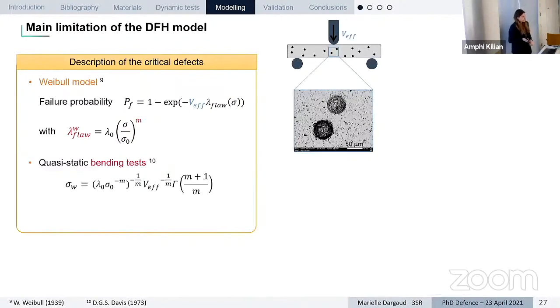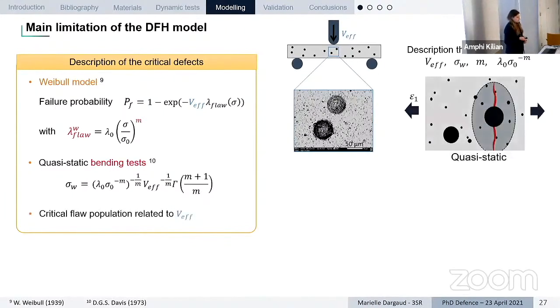In order to get and reach this m parameter, we need to do quasi-static bending test. So here we can evaluate this parameter m from the scattering of the results obtained from bending test. What we can see is that the parameters that we are going to obtain from this bending test highly depends on the effective volume that was loaded during the test and the most critical defect that is into this loaded